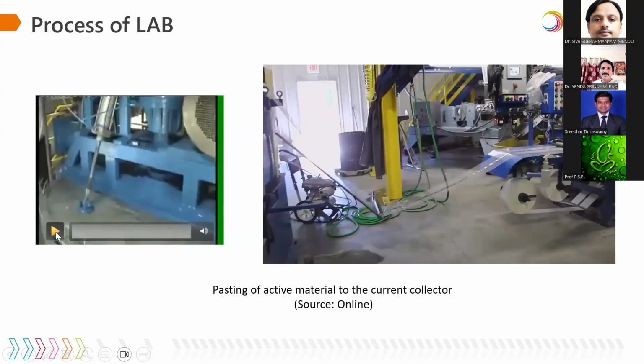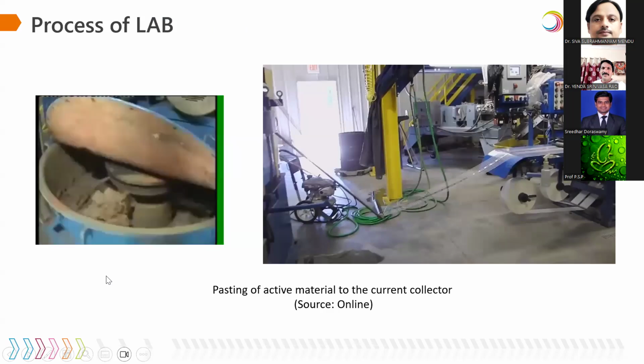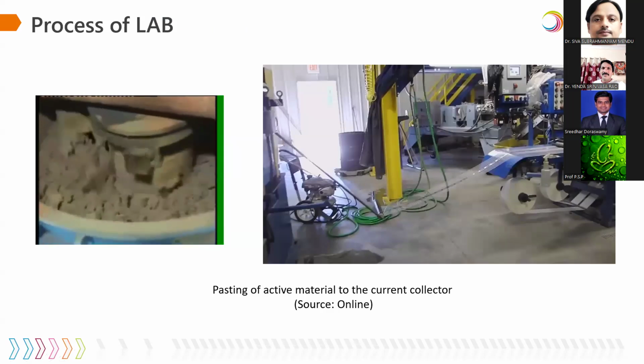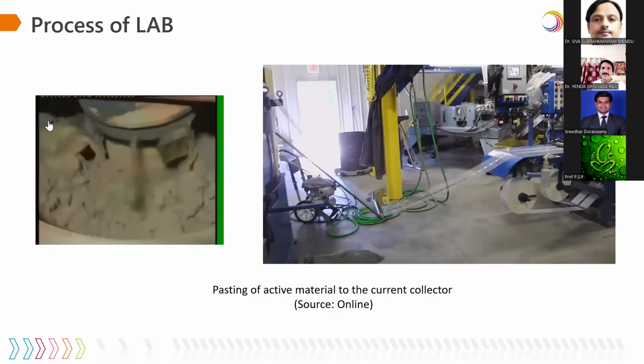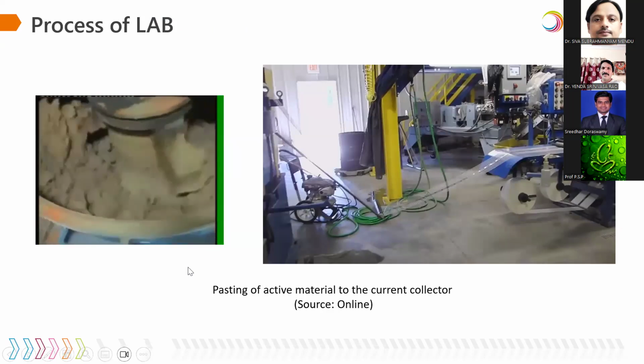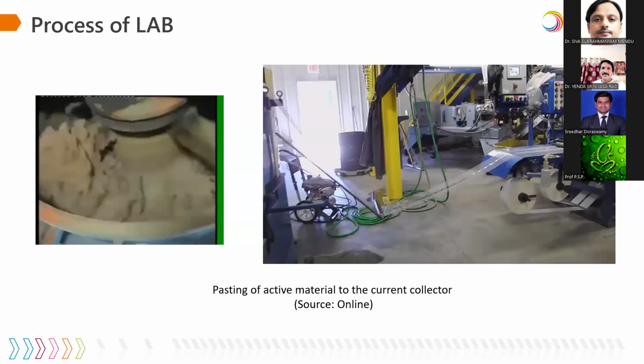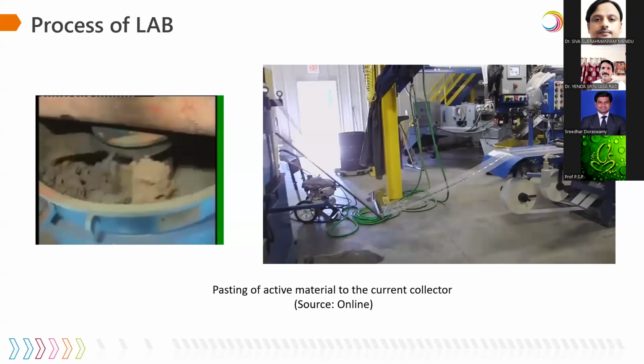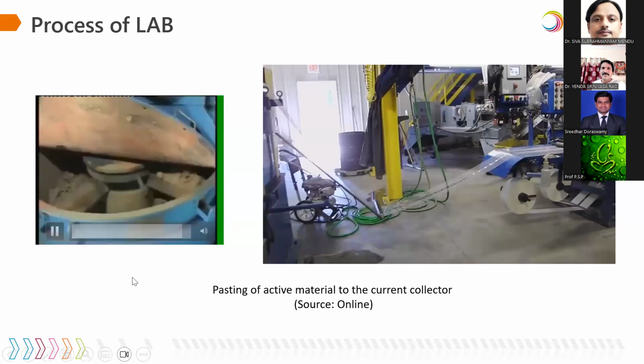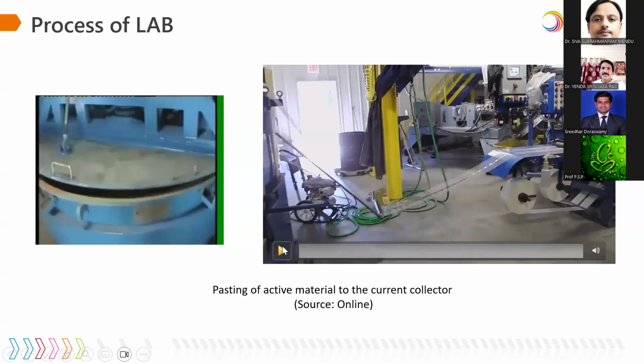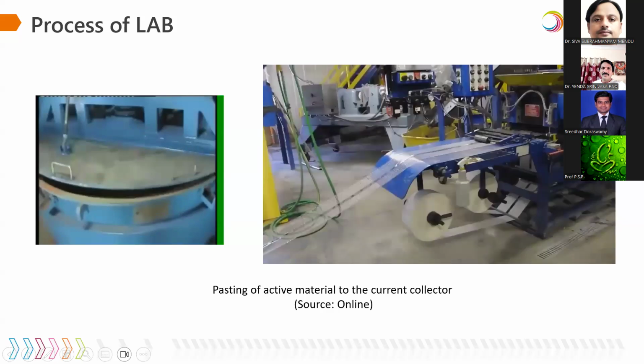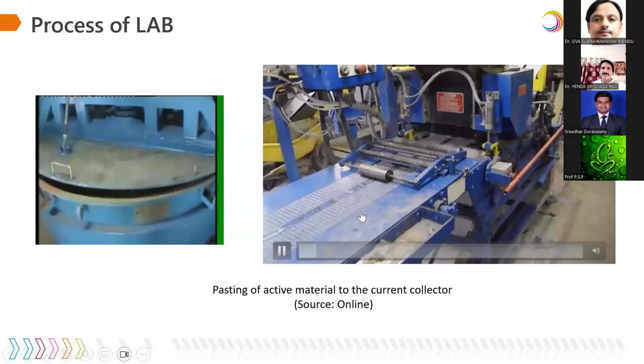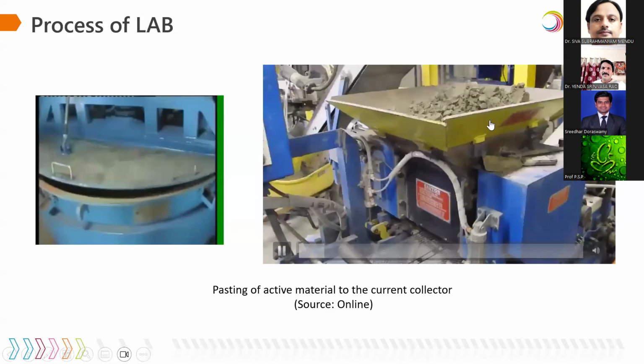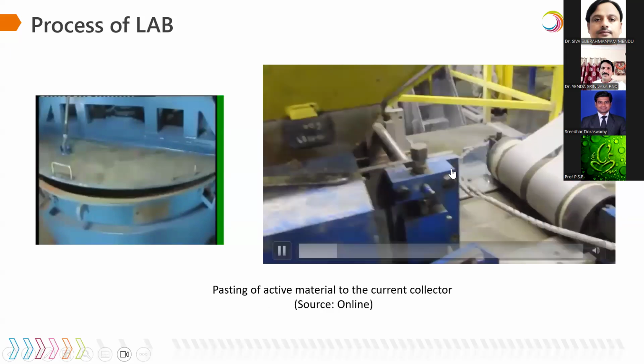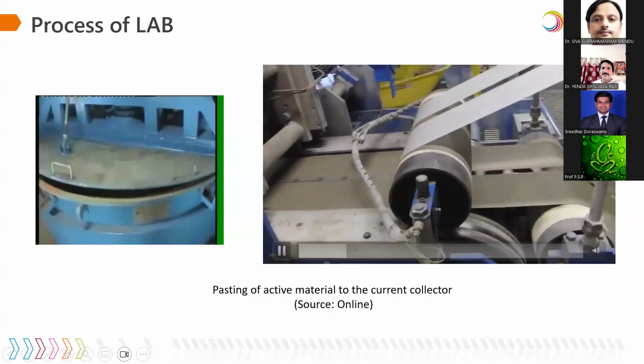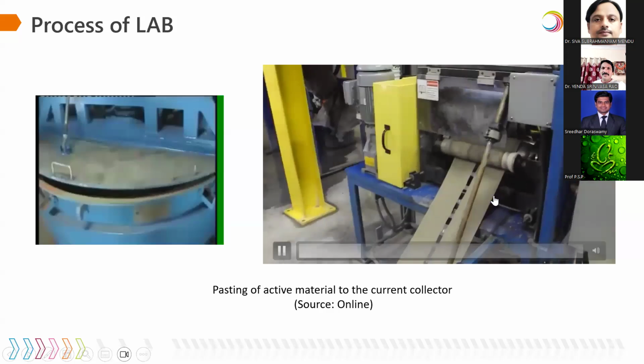So here is the paste mixing process of the active material preparation. The lead oxide powder is mixed with either 3BS or the 4BS crystals, that is tetrabasic sulfate crystals, in the PAM. In the NAM, the carbon and lignin are mixed in here. And here is the pasting process, where the mesh type grids are applied with the paste, which is the active material. And then it goes into the flash dryer.